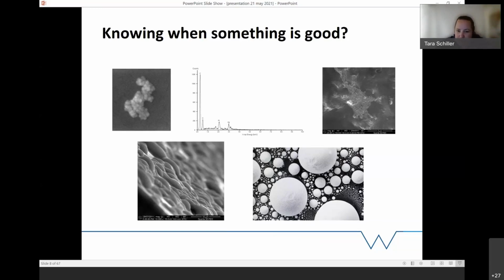This image here, the one below it, is an image we took of the surface of a hydrated silicon network that we'd made. You can see by the scale here at 10 microns that this surface isn't very smooth at all. So it's not very consistent. The image on the bottom right, if we were talking about microscopy, would be too much contrast, too much brightness, and we get a white and black image.